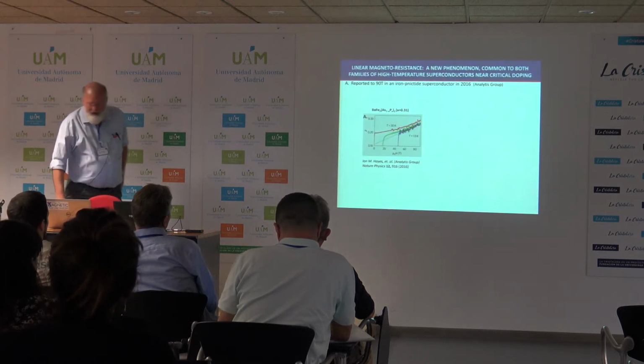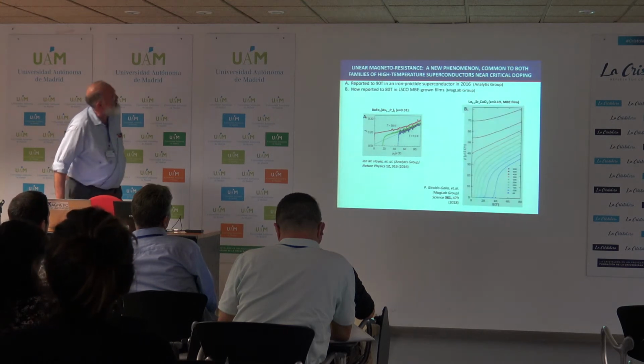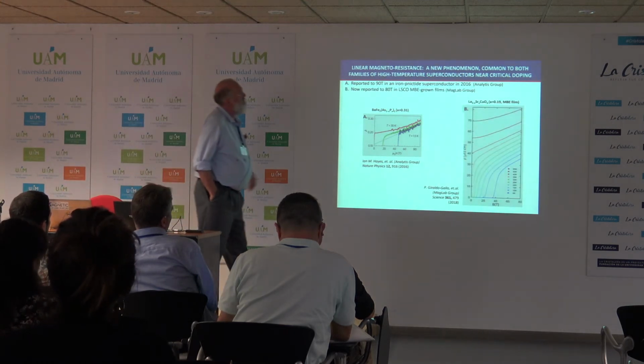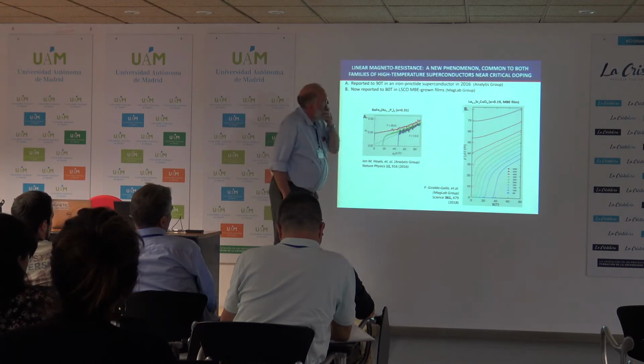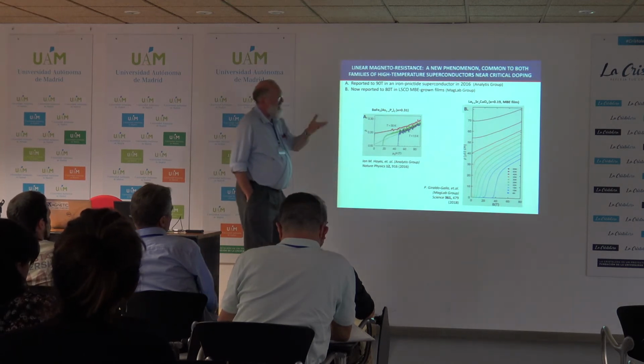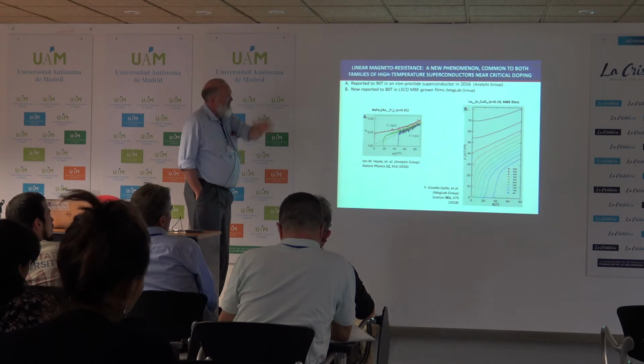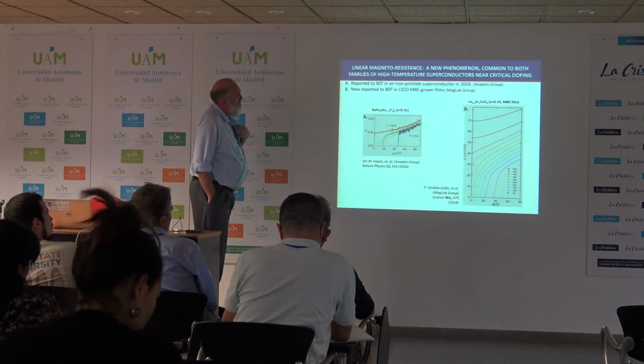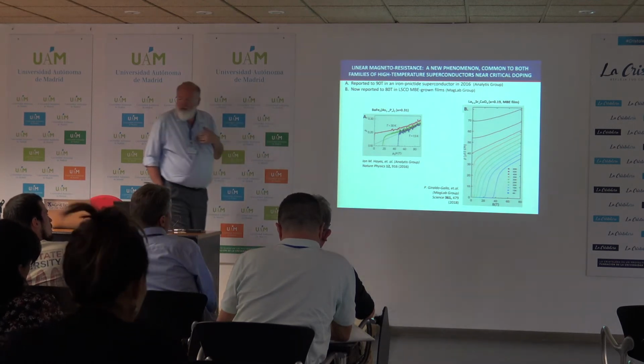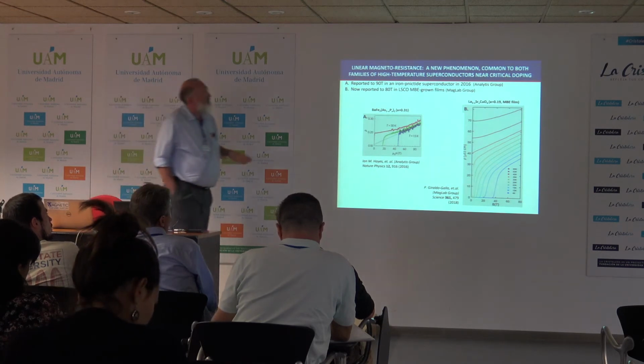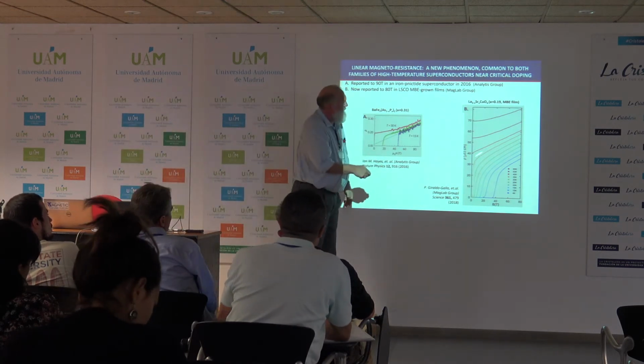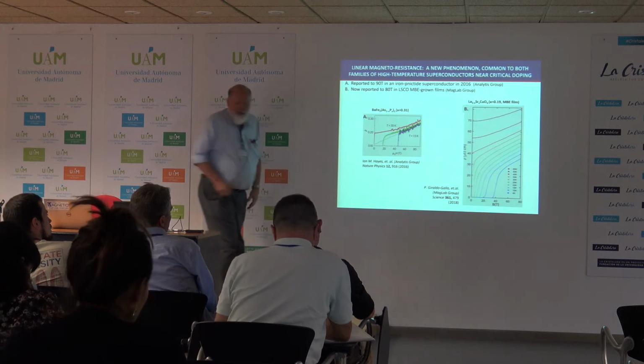And these are the data that I showed in the barium compound from James Analytis' group. And these are our data from LSCO thin films, the data that I showed you earlier, the temperature dependence, the linear temperature dependence that goes to the intercept. And you can see that this magnetoresistance is really quite linear as you get to the high field regime.